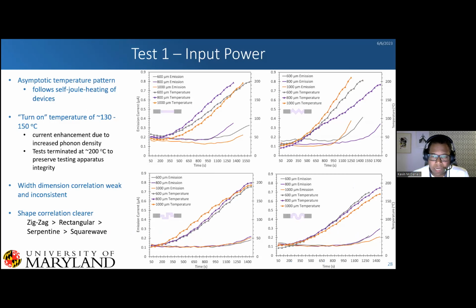And so for our first test, we just applied a field, and we applied a voltage across our devices, and basically allowed them to self-joule heat. And so you can see here, we pretty much have no emission, very little emission, if any. And then we start seeing it take off.